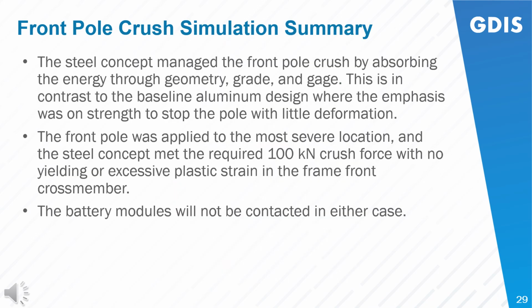So to summarize, the steel concept managed the front pole crush by absorbing energy through the geometry, grade, and gauge. This is in contrast to the baseline aluminum design, where the emphasis was on strength to stop the pole with little deformation. The front pole was applied to the most severe location in both cases, and the steel concept met the required 100 kilonewton crush force with no yielding or excessive plastic strain in the frame front cross member. Battery modules were not contacted in either case.